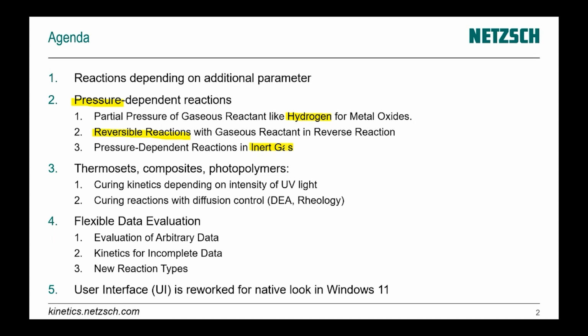The third part is our thermosets. Here we have a curing kinetic, again with a second parameter. And the second parameter for the curing, for the photopolymers, is the intensity of UV light. We are able to create a common kinetic model where the reaction rate depends not only on temperature, but on the intensity of UV light too.